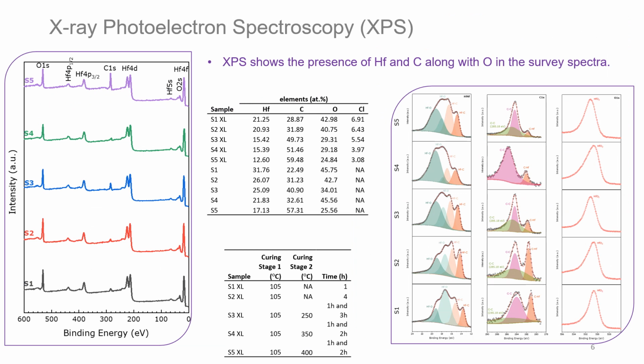X-ray photoelectron spectroscopy, or XPS, was performed to confirm the elemental composition and determine the chemical bonding of the elements in the synthesized hafnium carbide ceramics. The presence of hafnium and carbon along with oxygen in the pyrolyzed samples suggested the formation of hafnium carbide ceramics in the pyrolyzed samples. As presented in this table here, chlorine was observed in the cross-linked hafnium carbide precursors, which was completely absent in the pyrolyzed ceramic samples.